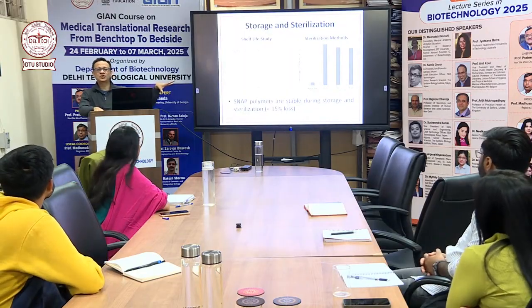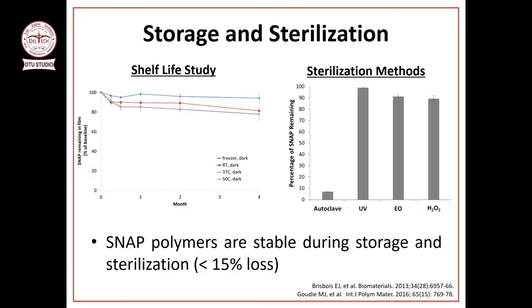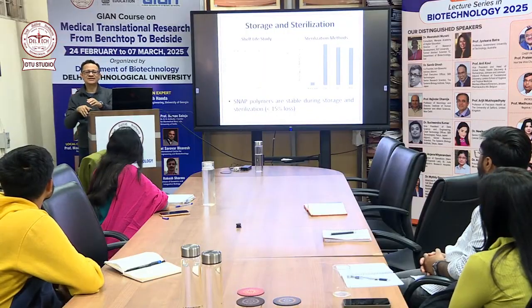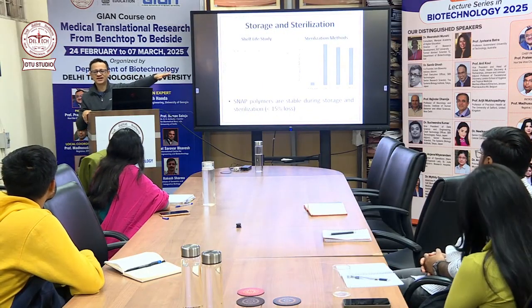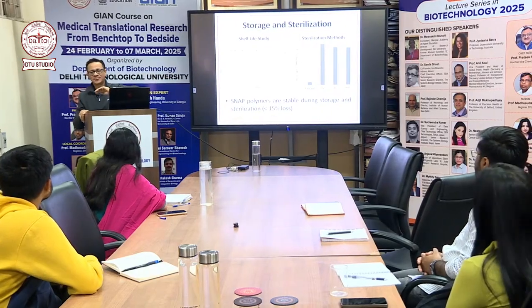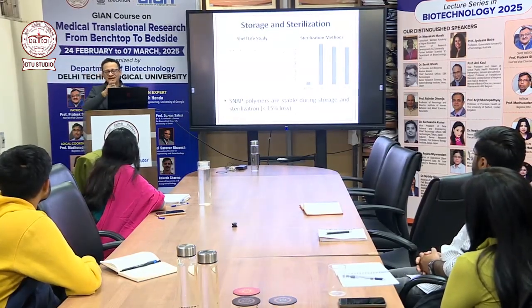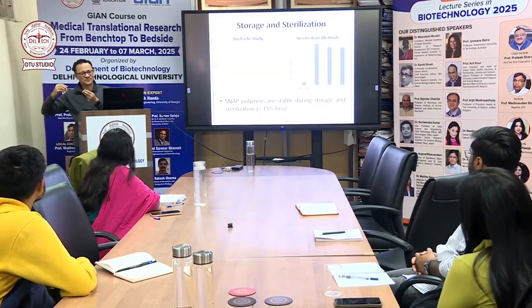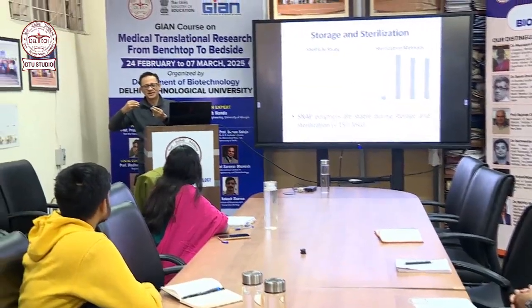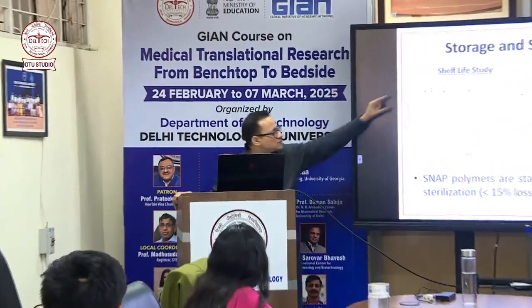Also, we did this study only to prove that if by chance a catheter is shipped, see, a catheter should be sitting at room temperature on a shelf or, let's say, in a refrigerator. But if you are shipping it, it better reach wherever you are sending it within a week or two. Worst case, it's a month. You might lose 15% of NO, but then you can keep it in the refrigerator and you will maintain that level. It should not just be sitting at 50 degrees for 3 months. If that's the condition, then maybe this is not the best technology.